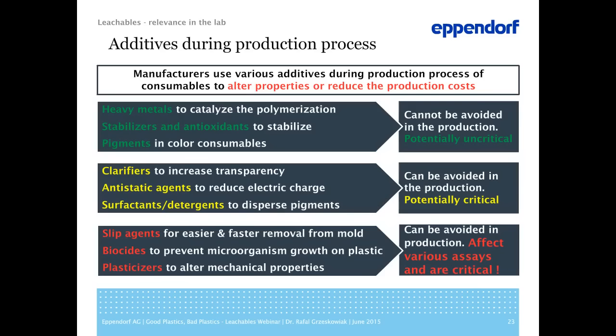And last but not least, at the bottom of the slide, the really bad guys. In red, you see the additives that have been shown in many publications to leach into the samples and pose a likely source of error in many assay systems. And the worst is these substances can be easily avoided and are added simply to reduce the production costs or make it faster. For example, slip agents are used to remove the consumable from the injection mold, similar to when one makes pancakes and puts butter on the frying pan. It makes it easier to remove the pancake from the pan, but it makes it fatty. And so the slip agents remain in and on the plastics and may contaminate the samples.